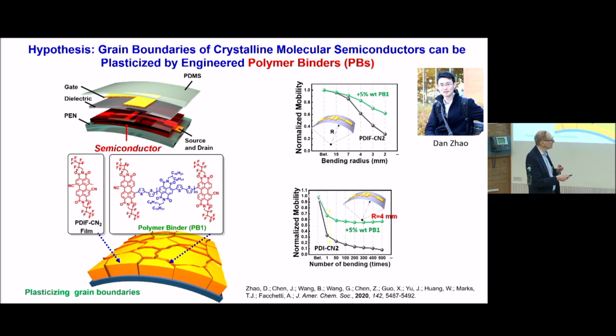So this is the semiconductor, and this is a crystalline film. Suppose we could fill the cracks with this material, where if you think of like likes like, this would want to associate with the grain boundary. And here in the middle is a flexible semiconductor, and this is the work that Dan did. So we basically plasticized the grain boundary, so we can make a transistor that you can bend back and forth.